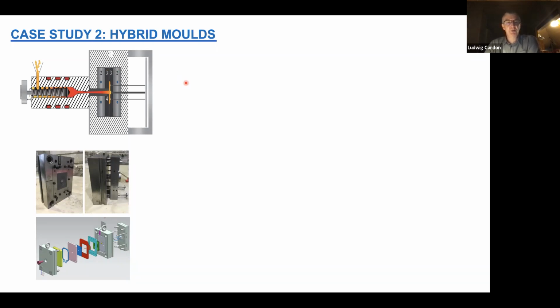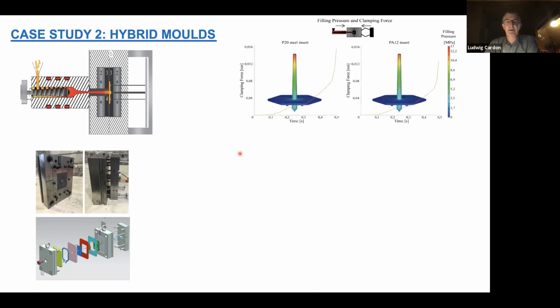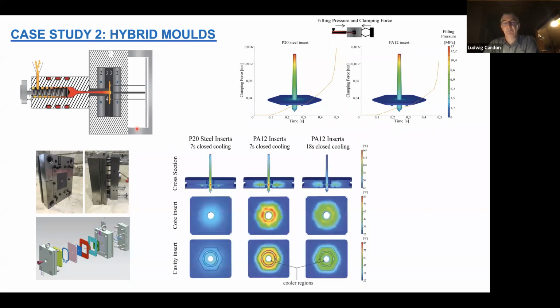People would say we can't use polyamide for a mold. Well, you see this setup design on the bottom. You see here the mold near the machine. What we then do is inject, in this case with a screw gate, and we have our part. It's a kind of play tool we produced, but we investigate, between steel and the polyamide insert, what the cooling behavior is and what the behavior of the material you inject inside that mold is.